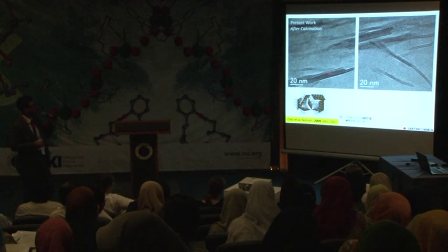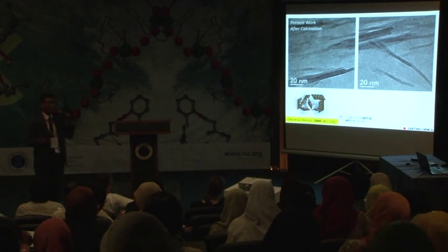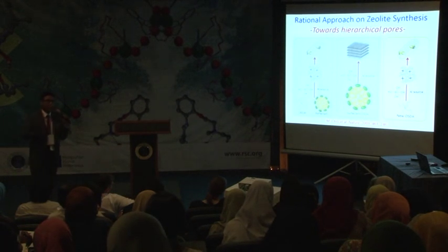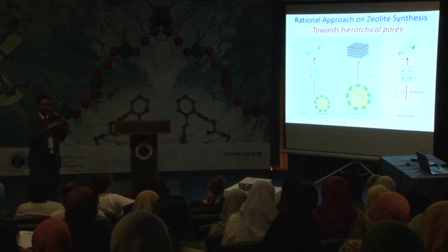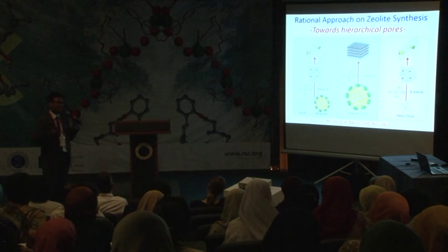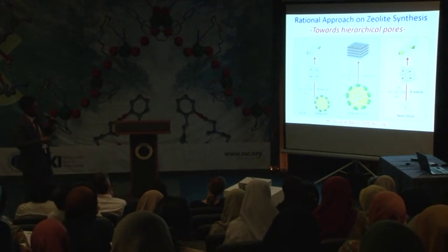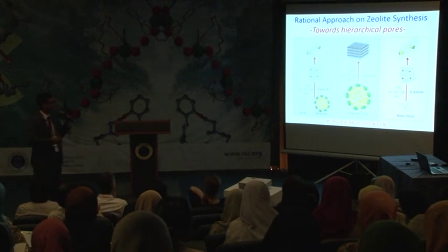We had collaboration before, but by having this nanosheet, very thin morphology of zeolite, when we remove the organics from the framework, some of the structure collapses. Yeah, so this is the disadvantage of having a very thin nanosheet. So that's why we don't want nanosheet. We want bigger, but still probably in the scale of nano, not 5 nanometers, probably 50 or maybe 100 nanometers. Okay, we try to find new organic SDA.